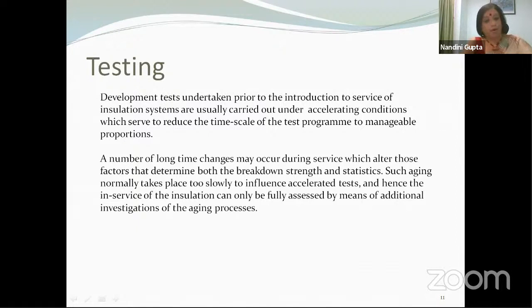So a number of long-time changes may occur during service, which alter those factors that determine both the breakdown strength and statistics. I will talk about these factors in a little more detail subsequently. But such aging normally takes place too slowly to influence the accelerated test, and hence the in-service behavior of the insulation cannot be fully assessed by this aging test.